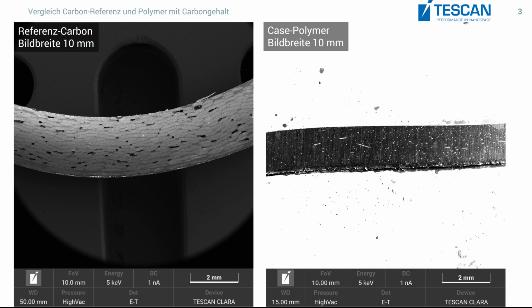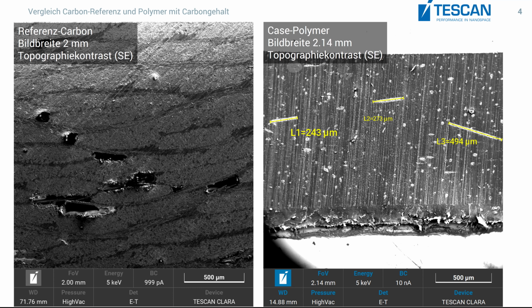Now magnified on the left, our carbon ring, and if you pay closer attention to the bottom, you can see a scale which indicates the raw size of 2 mm, and on the right side we can see the case polymer again on the same scale. For ideal comparison, Tescan performed some grinding on the surface just to be able to compare both specimens the same way. If we zoom in further, on the left side again the reference carbon, which is our carbon ring, and on the right side you can spot our case polymer. On the right side you can already see some white dots and also some of those yellow lines, and those are the carbon fibers inside the polymer.